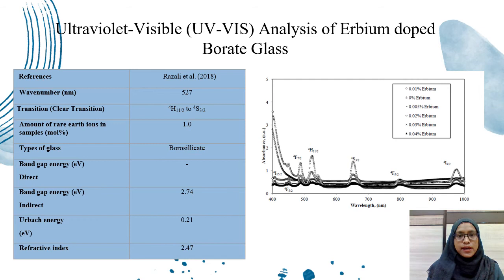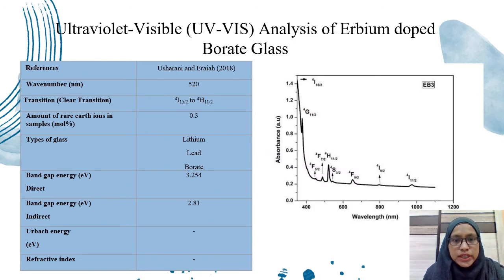UV-VIS by Razali et al. shows that the clear transition is from 4H11/2 to 4S3/2. The amount of rare earth ion in the sample is 1.0. They are using borosilicate glass. UV-VIS from Usharani and Eraiah, the clear transition is from 4I15/2 to 4H11/2, using the amount of rare earth 0.3 mole %, and using a glass of lithium lead borate.